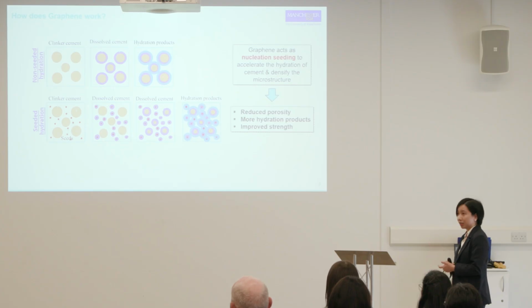At the same time, graphene is also a very efficient nanomaterial. Even adding a tiny amount of graphene into bulky materials such as concrete will make a significant change to the properties of the concrete. When we add graphene nanoplatelets to the cement paste, they act as nucleation seeding to accelerate hydration, allow the formation of more hydration products, and densify the microstructure of the cementitious material, which finally results in improved strength for concrete.